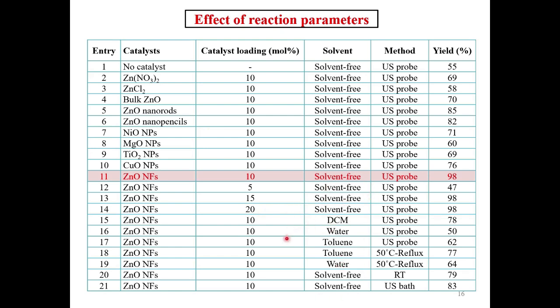Different solvents we have also used, that is DCM, water, toluene, and solvent-free condition, even at room temperature or in absence of reflux, up to 50 degrees centigrade. And when we compare all these data previously done by the researchers and our group, zinc oxide nanoflowers, when we have used 10 mole percent under solvent-free condition in presence of ultrasound cavitation technique or ultrasonic probe, the yield of the product is 98%.